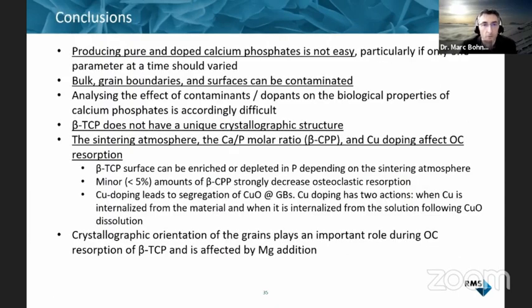And I would like then to conclude by saying that basically producing pure and doped calcium phosphate is not as easy as it may appear. The bulk, the grain boundary and the surfaces can be contaminated. Beta-TCP is a highly used material, but apparently the crystallographic structure is not as defined as one may think, and possibly beta-TCP is actually a mixture of different compounds. And the sintering atmosphere, the calcium to phosphate molar ratio, in particular pyrophosphate, and copper doping affect the resorption.